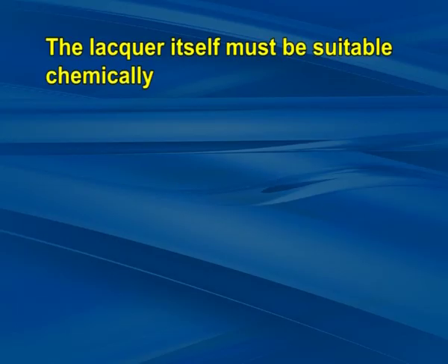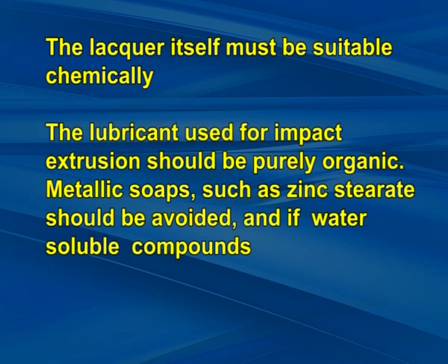Properties. The lacquer itself must be suitable chemically. The lubricant used for impact extrusion should be purely organic. Metal soaps such as zinc stearate should be avoided, and if water soluble compounds, that is ethoxylated lanolines, can be used, so much the better, as subsequent degreasing is going to be more effective.